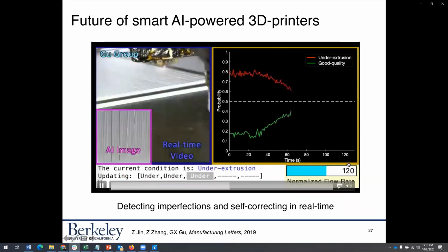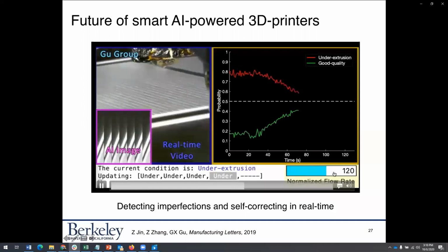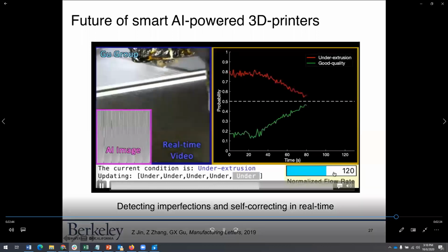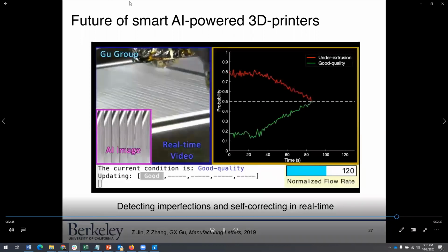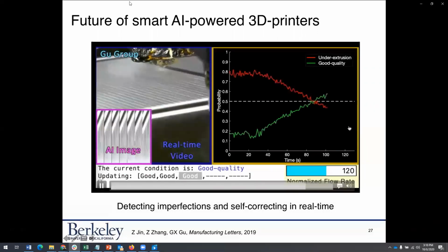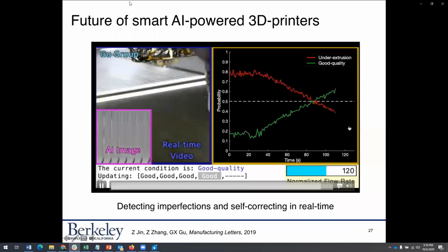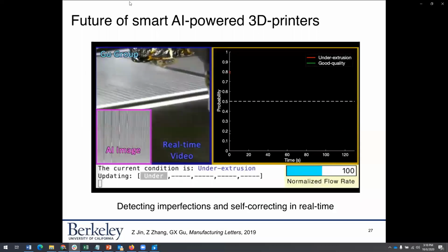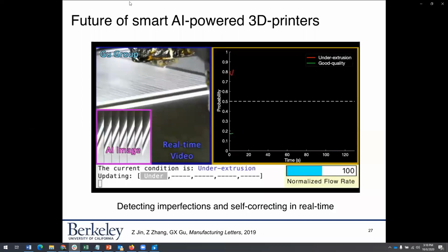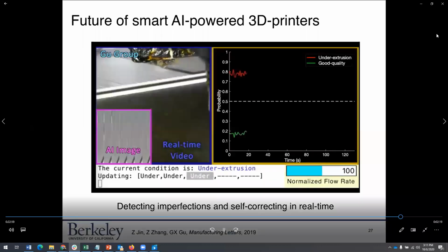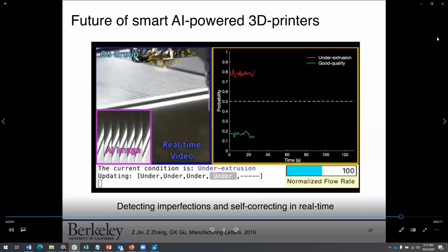Earlier it was a flow rate of 100. Because we noticed that it was under extruded, it started to increase the flow rate to correct for these issues. And then after it increased the flow rate, you can see that the probability of the sample becoming good is starting to increase, and the probability of being under extruded starts to decrease. So this is how our platform works.